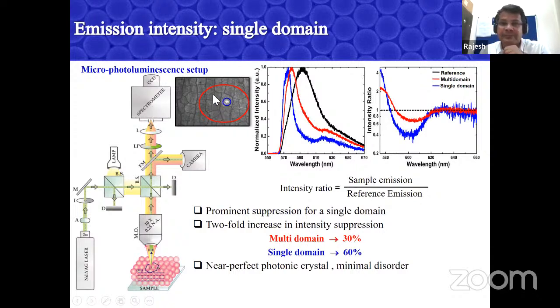And we did measurements initially by using a lens from the large area and also within a small region, basically within a domain. So before doing measurement, first we look at the intensity versus wavelength for a dye, the reference sample, which is a dye suspension. And you can see that it gives a nice photoluminescence or spontaneous emission around 600 nanometer. And then you trap this light source within the photonic crystals, which is emitting at the band gap at 600 nanometer. And you do a large area measurement, you get this red curve here.